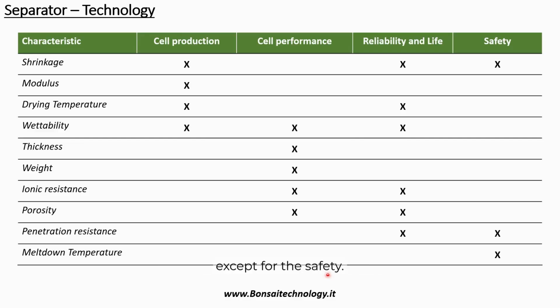That is important for quite everything except for the safety. So it's important for cell production, cell performance, reliability, and life. The wettability is the capacity of the separator to be wet by the electrolyte. The electrolyte goes into the separator porosity. If the separator is wet completely and in homogeneous way by electrolyte, during the formation that we see later on, we will have a very thick and homogeneous solid interface layer of electrolyte. And this allows to have even very homogeneous performance through the battery cell, and even have a reliable product, because we can measure the performance during the working life and we can understand what's happened.